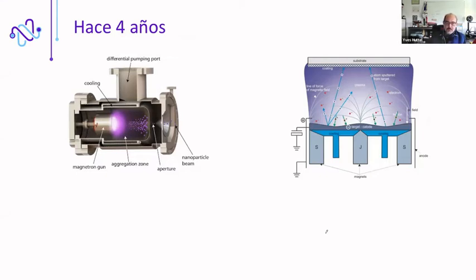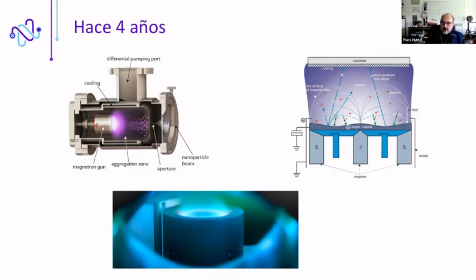Four years ago, we were facing another problem. Our cluster source is based on a magnetron, as I told you. And the magnetron has magnets and a target that you erode with the plasma in order to eject the atoms. Because of the design of the magnets, the plasma is concentrated in what we call a racetrack, which means that most of the atoms will be ejected from this circular place. And this has a very strong effect on the efficiency of the magnetron.